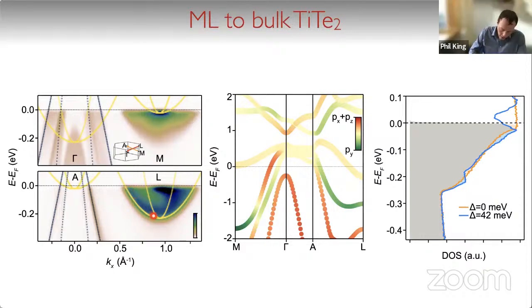So if you look here, the bottom plot is at a photon energy that's nominally probing the L point, and the top plot at a photon energy nominally probing the M point. Our interpretation is that this band here disperses as a function of photon energy or KZ to form this sort of weak minimum here. And the additional spectral weight that we see here is simply a KZ broadening effect. You know, there's a large density of states associated with this little band just below the Fermi level at the M point. And so we see a bit of that in the L point measurements.